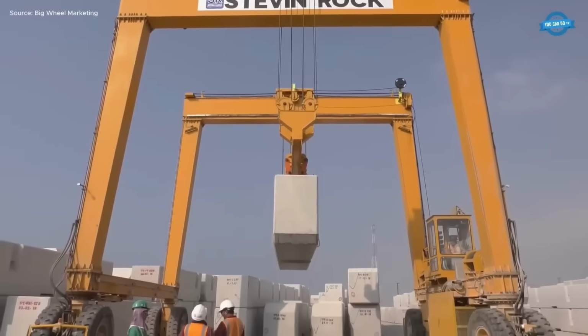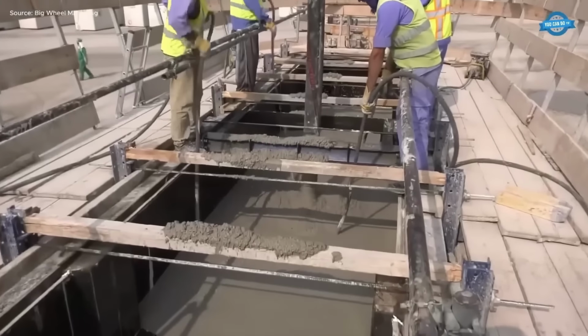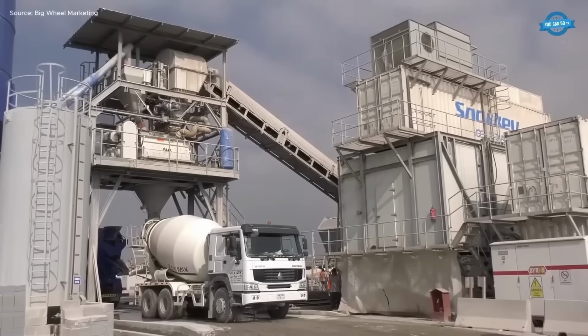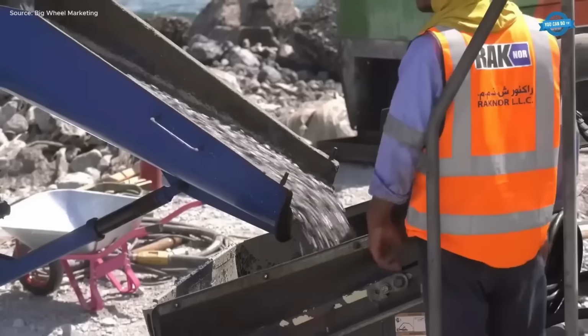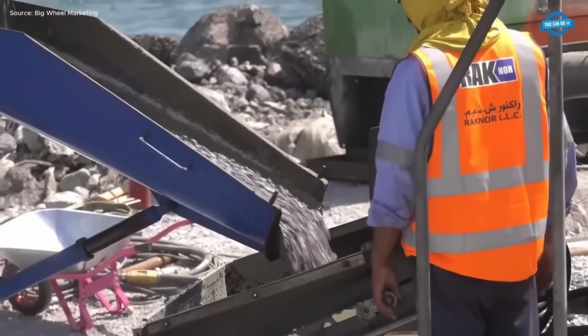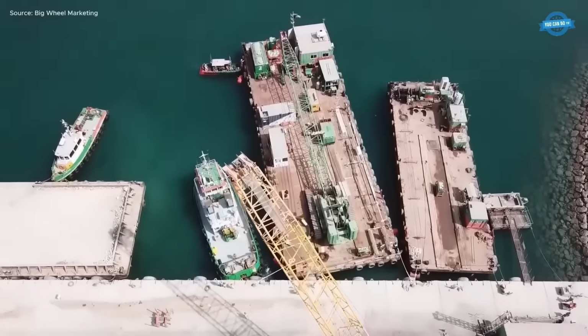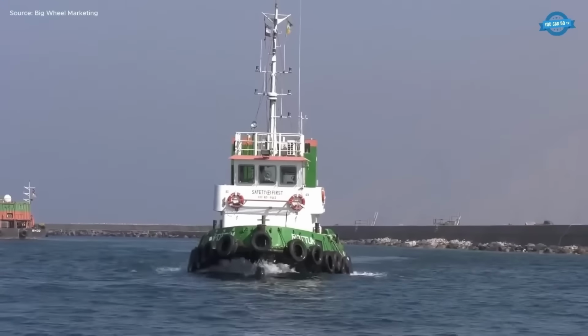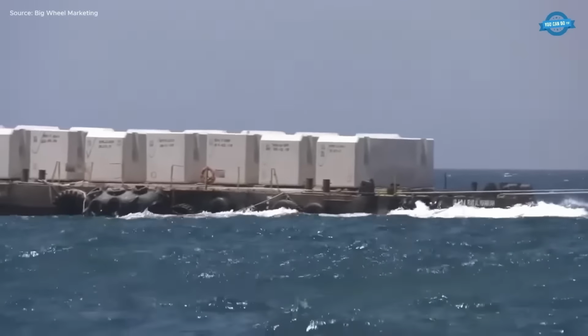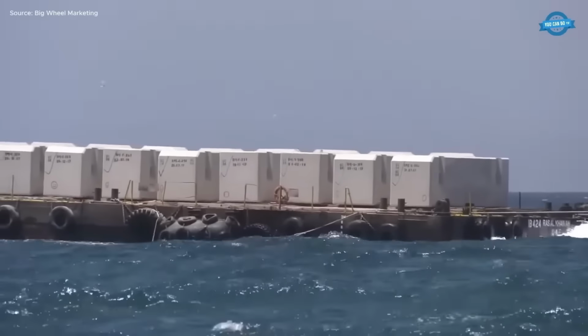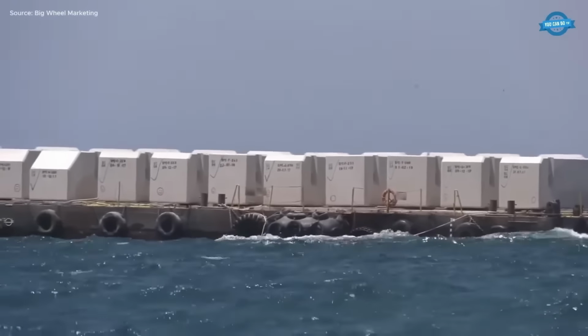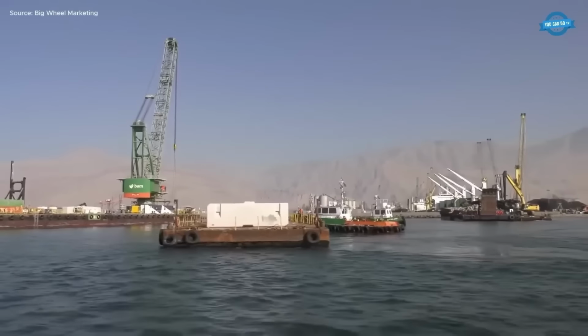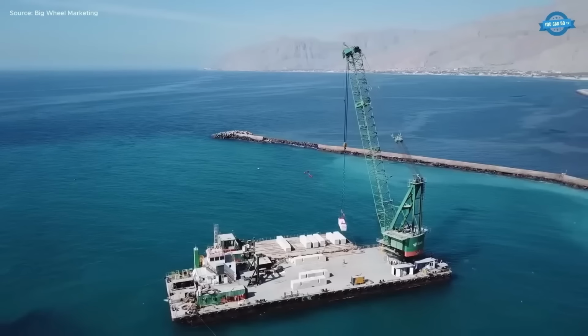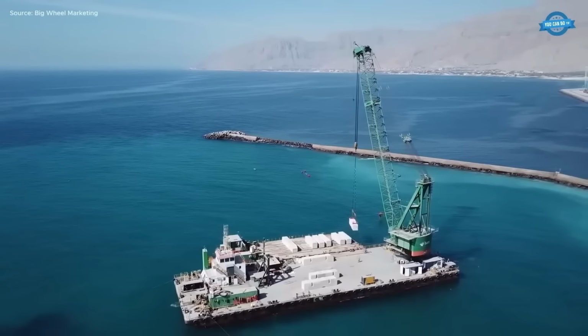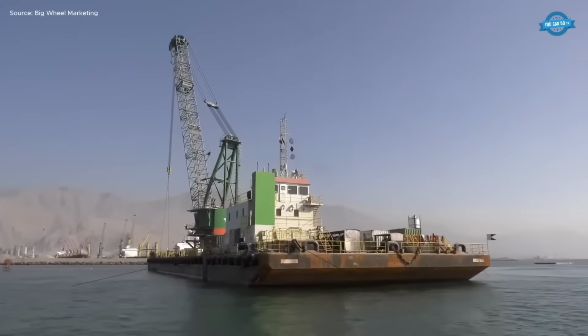The construction process involved the fabrication of over 5,000 specialized concrete quay blocks, each weighing approximately 80 tons. These blocks were cast using a tailored concrete mix, designed to achieve high durability and strength, in a marine environment subjected to thermal variations exceeding 40 degrees Celsius during the casting period. To optimize curing and reduce thermal cracking risks, casting was scheduled primarily during nighttime hours.